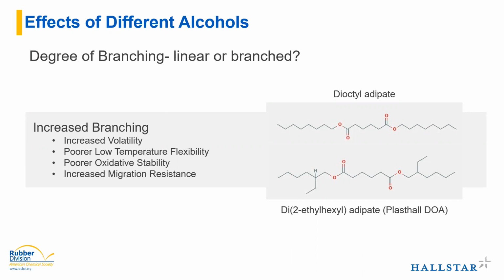But just to give an illustration here, these two materials are the same molecular weight, have the same chemical backbone as far as carbons to oxygen ratios, but the top material has no branching, the bottom has some short branches coming off the side, just to illustrate what I mean by branching. When you increase branching but maintain the same molecular weight, you tend to see increased volatility. The way that the molecule is arranged increases the volatility when you have branches coming off of it. You'll see worse low temperature flexibility.